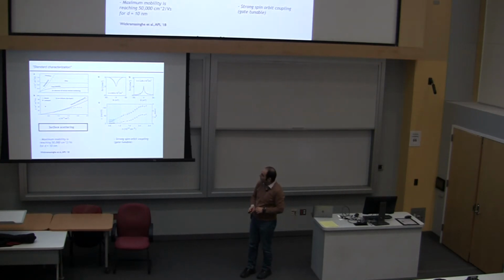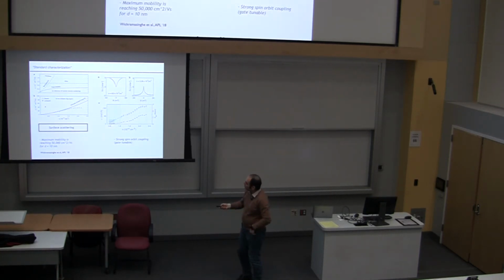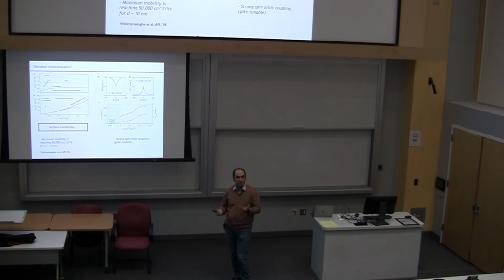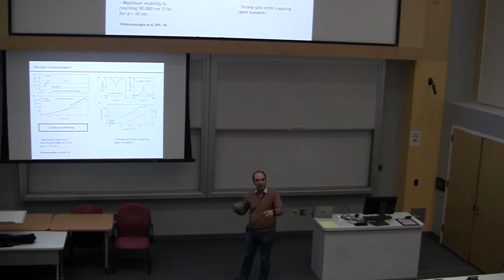Let me show you some data. I took it out. But basically, the mobility now, the maximum reaches 50,000. We can actually characterize the background impurities, the interface, the alloy that we have in the chamber. How will each of these limit the mobility of my sample, right? It turns out, not surprisingly, it is all surface scattering, right? Because your quantum well is now near the surface. That's the dominant effect. Basically, everything else that mattered for gallium arsenide and other things is not playing that much of a role.